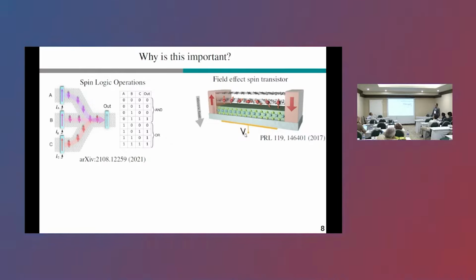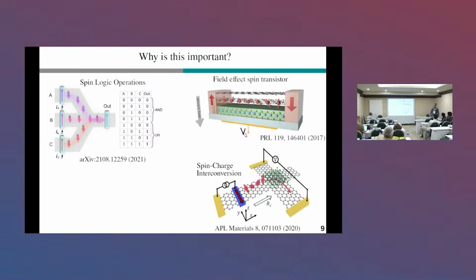And what is important here is the short-rangeness of the proximity effect. So only the lower layer is proximitized. And on top of that, with the electric field, we can then switch the band structure. So we can effectively turn on and off spin-orbit coupling in the transport channel. And this can be used as a field effect spin transistor. Moreover, we have already seen that such heterostructures can also be used to interconvert between spin and charge currents, so without the need of conventional ferromagnetic electrodes, we could actually switch between spin and charge currents.